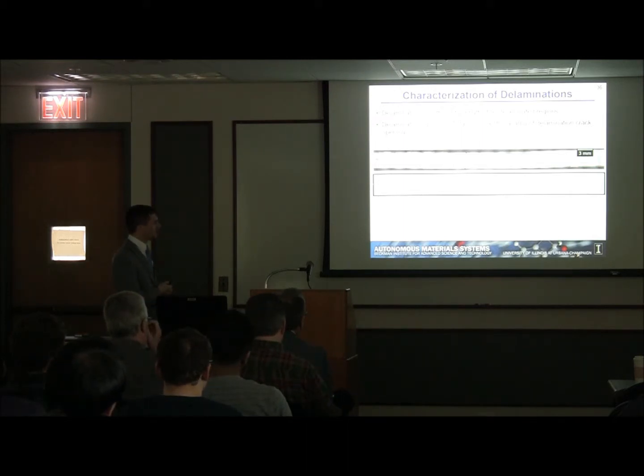So our hypothesis was that 3D composites might have less damage because of that through-thickness tow compared to the 2D composites, and that might be why the residual strengths are higher. So we looked at the delamination sizes of these samples after they had been impacted. And we looked at 2 different metrics. One metric is the delamination length, and so that's simply the total length of the delamination in these images. And we also looked at the delamination opening, which is the total cross-sectional area of the delamination crack opening in these images. So all the pixels summed together, multiplied by the calibration of the single pixel.